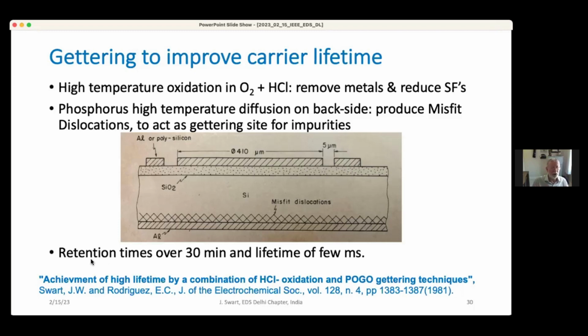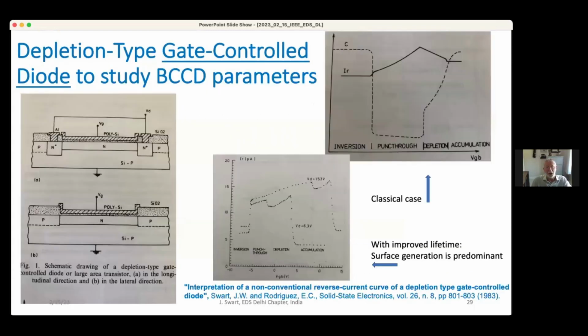And with that, we got retention times for the MOS capacitor, by pulsing, of over 30 minutes. You have to wait more than 30 minutes to return to equilibrium, and we extracted lifetimes of a few milliseconds. And that's why we had a different reverse current behavior in the diodes.